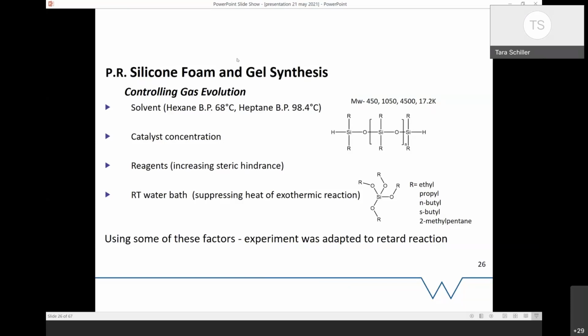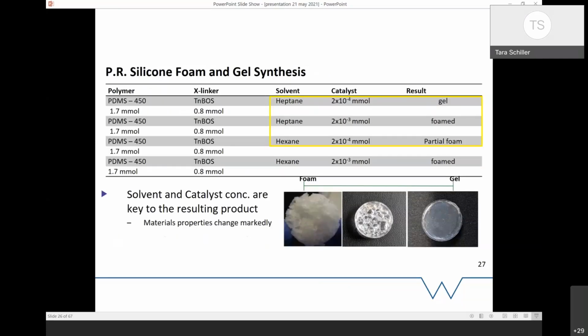We also played around with molecular weight as well. So one of the things we noticed too, it went off like an absolute rocket the first few times. Room temperature water bath, we did try ice baths but then it slowed it down too much in that sense. But yeah, quite a few things we were playing around with to try and work out what we could get. So you can see on the left side, there's a nice fluffy, fuzzy looking thing that was quite brittle, to be honest. Basically could pulverize by hand quite easily.